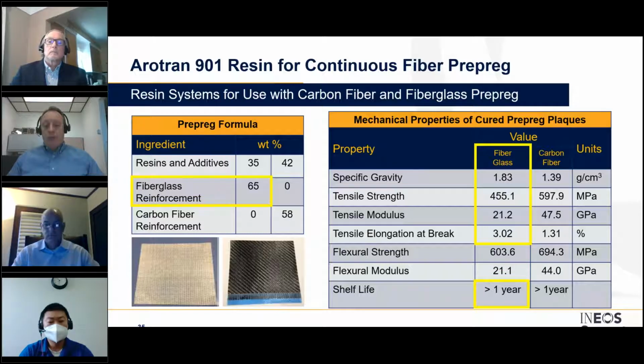In the case of the prepreg with fiberglass reinforcement, we made panels directionally balanced in the XY direction that showed very high performance in tensile strength, despite a pretty typical specific gravity of around 1.8. You can see the tensile strength of 455 megapascals and a modulus of 21.2 gigapascals. As expected, the tensile elongation at break was relatively high when compared to the carbon fiber panels.